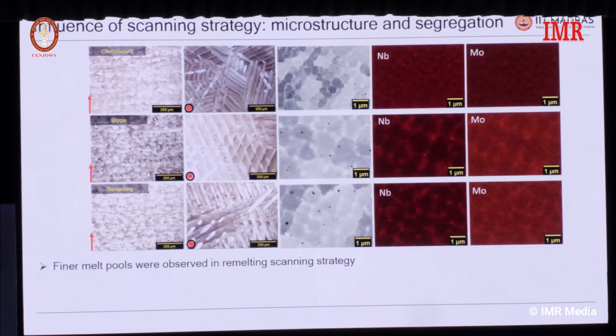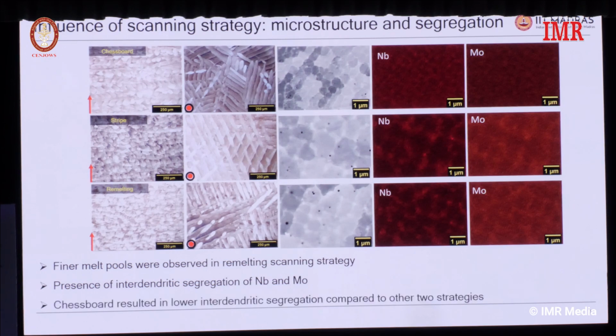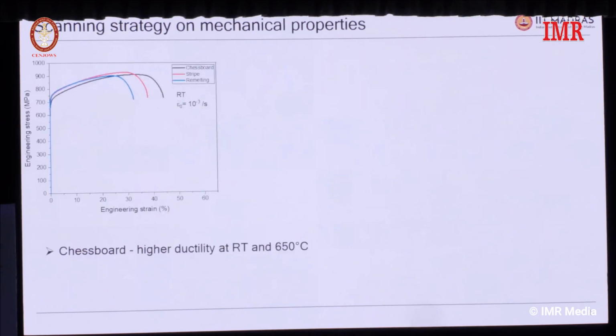So to give you an idea here, I showed 3 different scanning strategies. The top one is the chessboard, then the stripe, and the remelted one. What you can see is that as compared to the chessboard, stripe and remelting have a certain amount of segregation, which is ideally not good for us. Though you have finer melt pools in the remelting, it is not sure whether that is the right thing for our properties. Chessboard has a lower dendritic segregation.